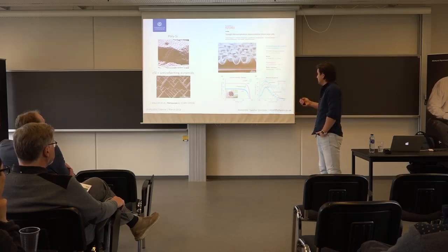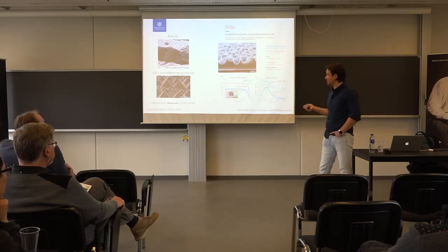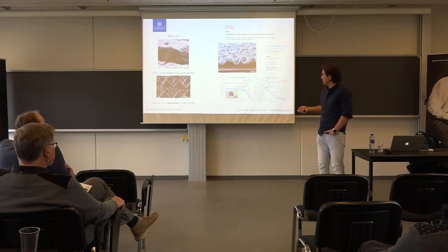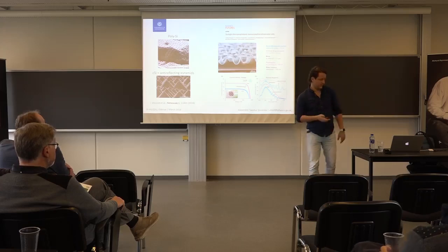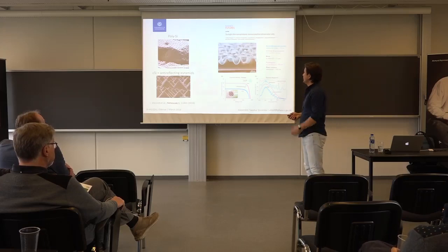So typically you would have 200 microns, and you would have an efficiency of 22% or something. So here with the sub-micron effective thickness, we are losing the efficiency only twice, let's say. But this is just to demonstrate that the method could be used in completely different contexts if you are thinking of applying it to your own research.